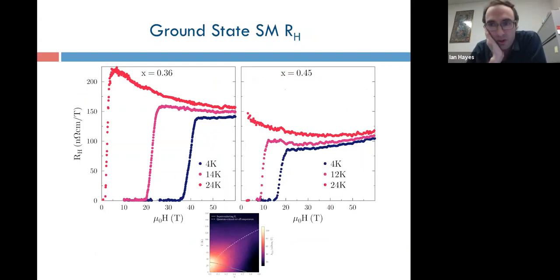So let me start by showing you what the data looks like at low temperatures. These are just slightly overdoped samples, 36 and 45% phosphorus doping, so they live around here. You can see a strong decrease in RH at moderate temperatures of 25 Kelvin or so. And then that decrease definitely weakens as you go to lower temperatures. At higher fields, you can see that the increasing RH is setting in again. And in between there, there's sort of a balance between the two.